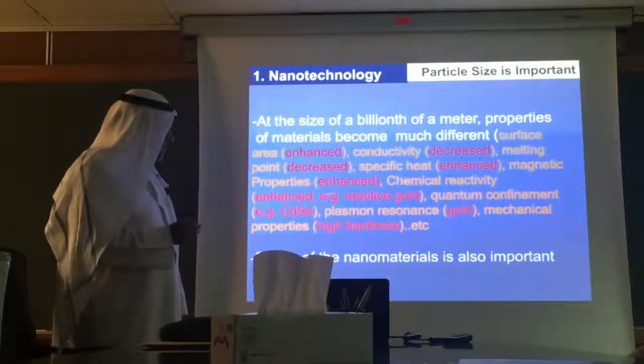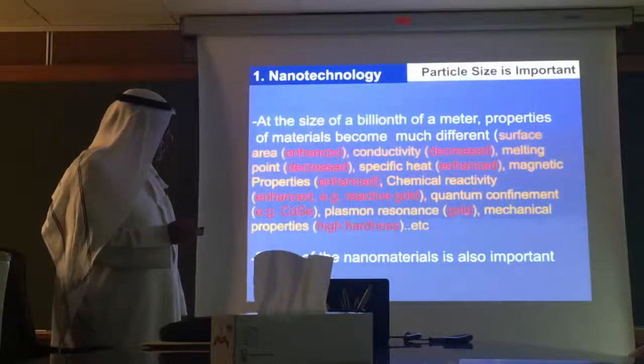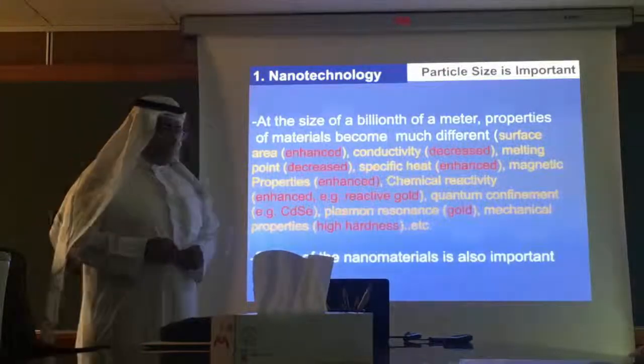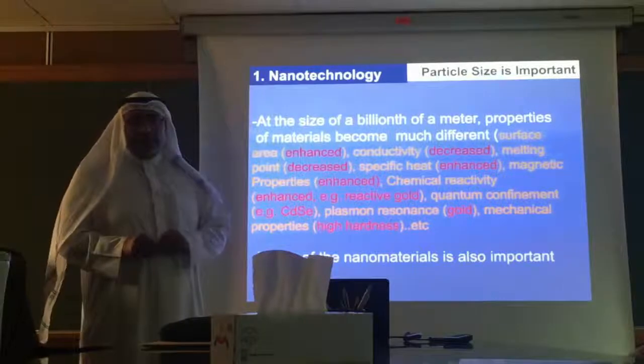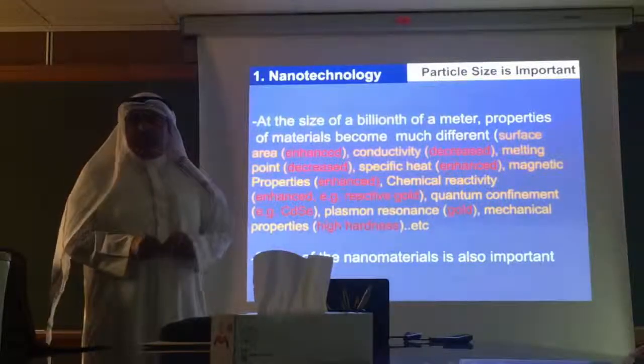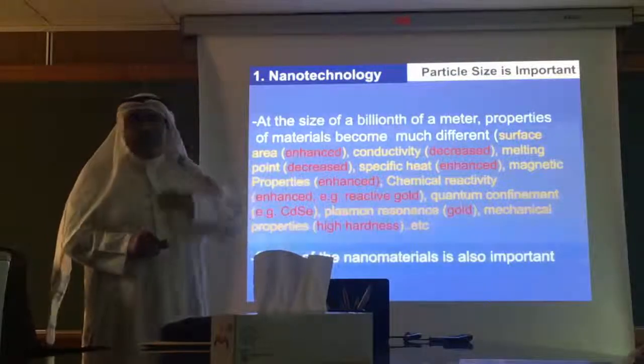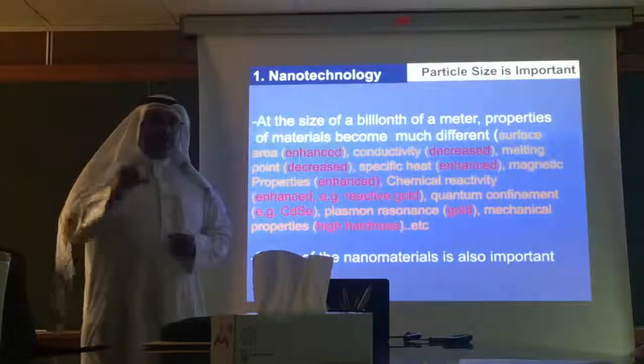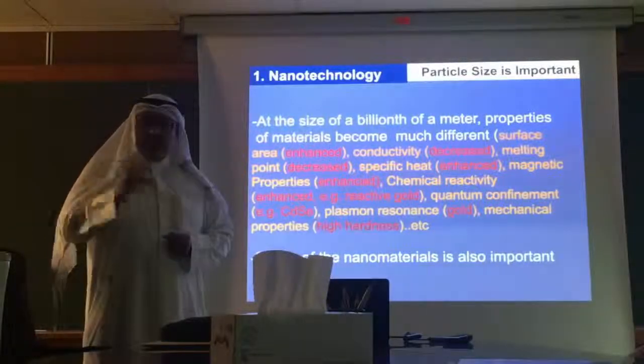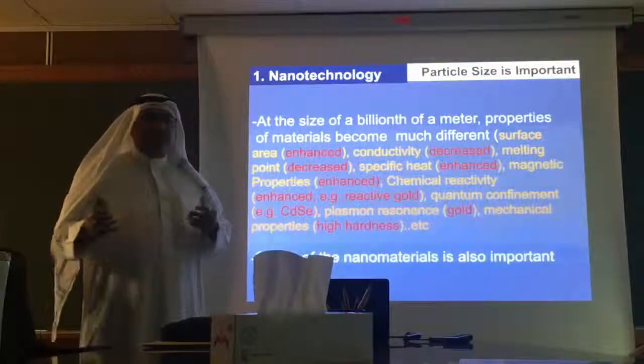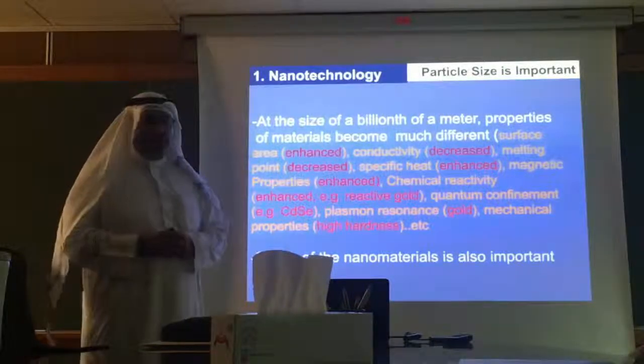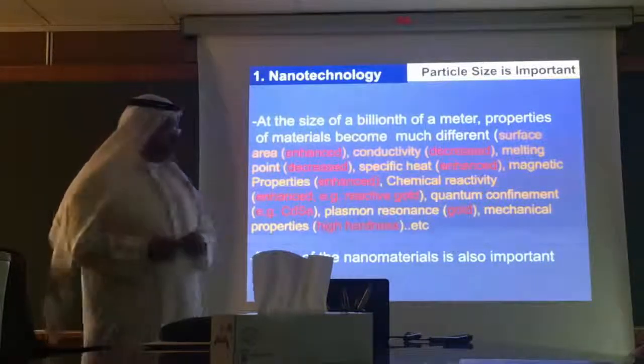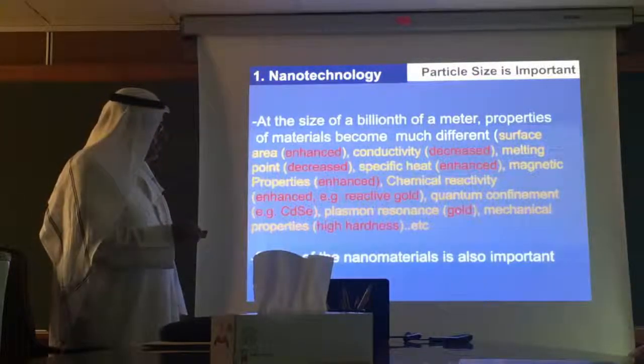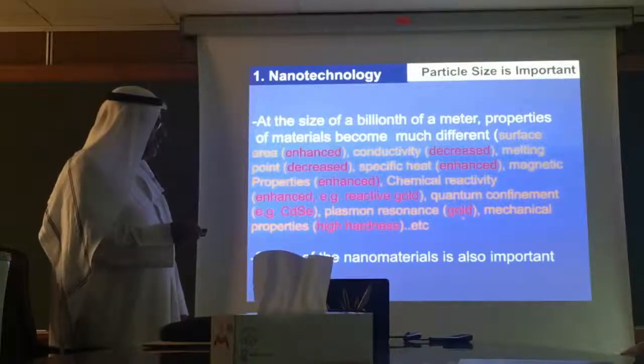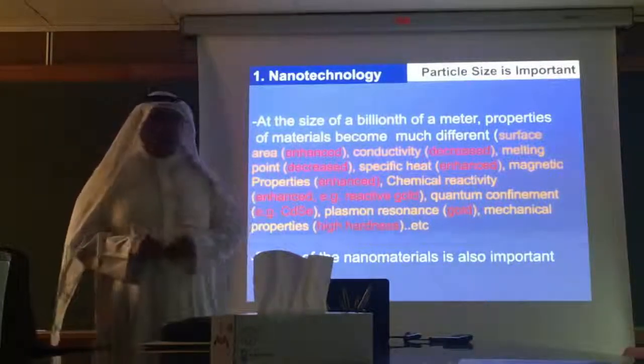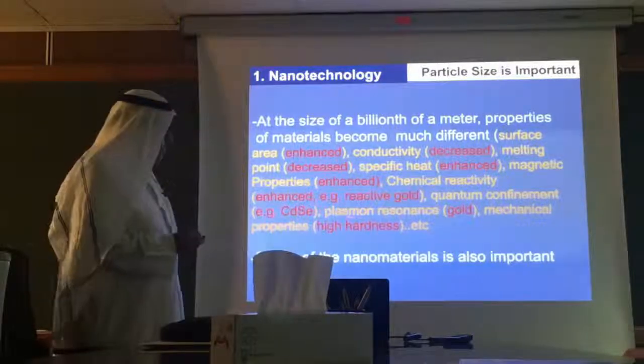The plasmon resonance, this is very important for gold nanoparticles because they use it to kill the cancer cells. They just put antibodies on this gold nanoparticle, and then they send it to the cancer cells. And then by exposing it to just normal light, there will be oscillation of the electron cloud of the gold. And by this oscillation, the temperature increases dramatically. It can reach maybe 1000 degrees. And this will immediately kill the cancer cell. So there is huge research, and people are saying, we know that gold is very expensive and precious, but if you make it nano gold, it will become even more precious because of this application.